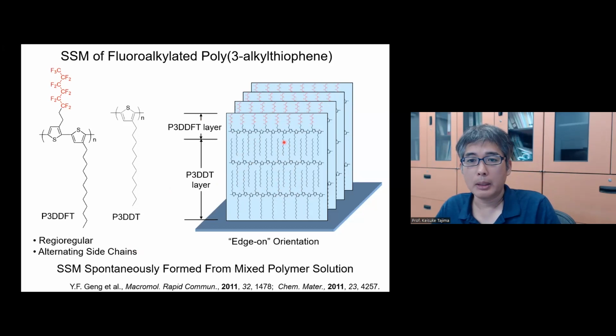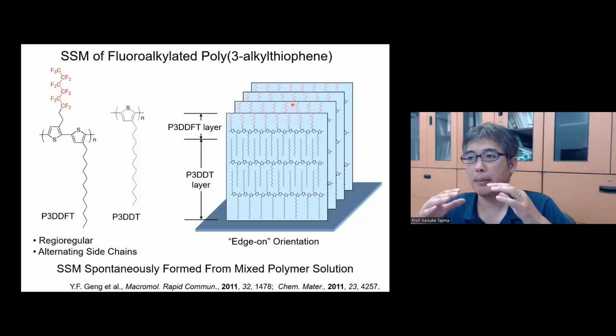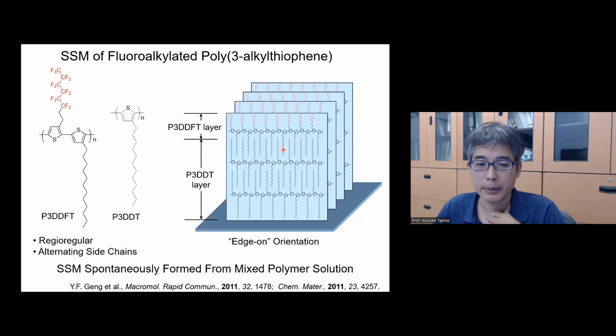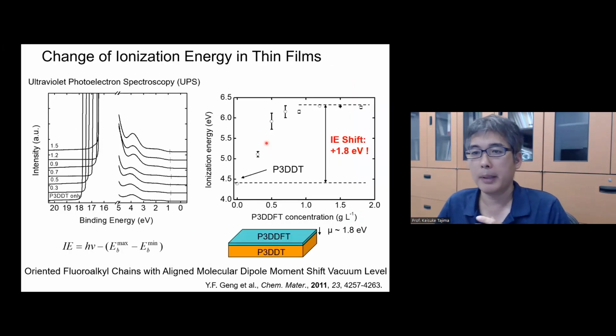And the important point compared to the previous case is the orientation of the polymer. This P3DDT tends to have the edge-on orientation. That's why we designed this molecule to match the structure of the bulk, so the fluoroalkyl chain could have a very high density at the surface of the film. So it behaved very well.